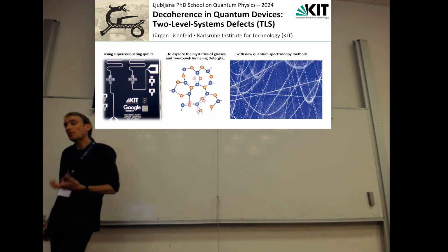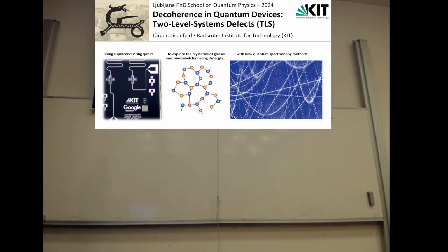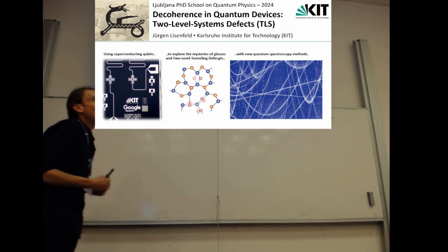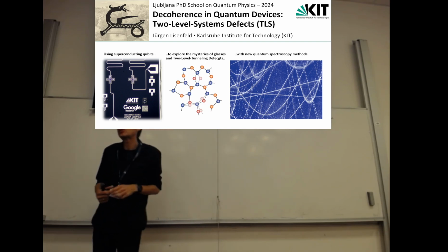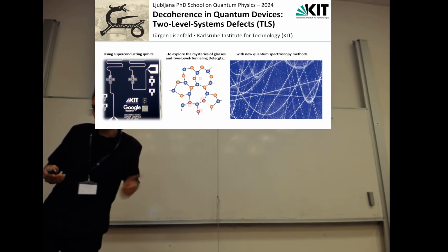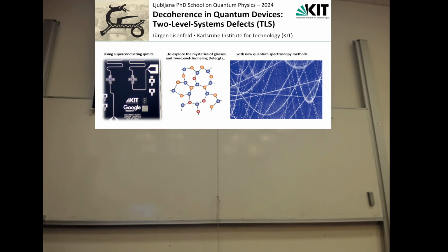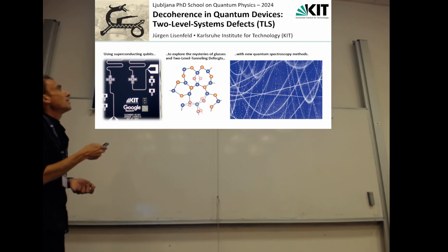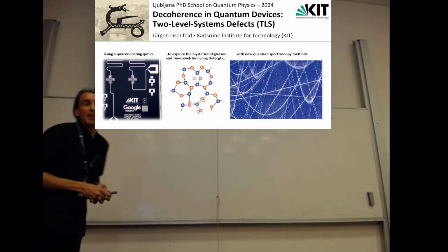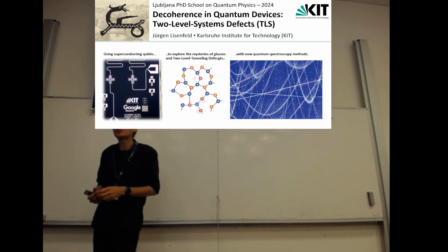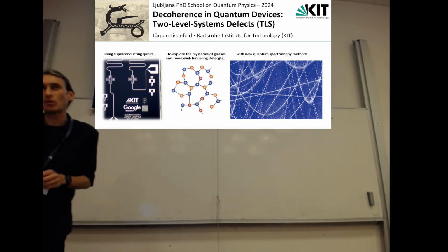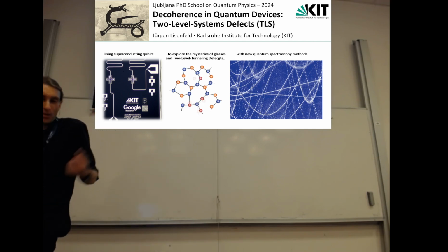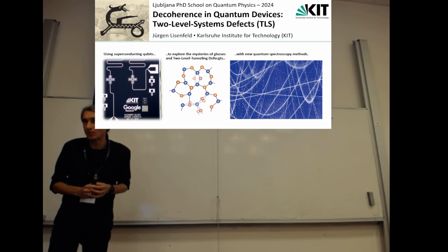And this is actually one of the biggest problems we have if we want to build a quantum computer. You know, there is some effort to make a superconducting solid-state quantum processor, and we could already do it if we wouldn't have these parasitic two-level systems, these parasitic quantum systems. I already called them two-level systems, TLS. This is the topic of this lecture. It turns out that they affect a large variety of different devices, especially quantum devices and high-precision devices. So it may be a rather big challenge which we have in technology.